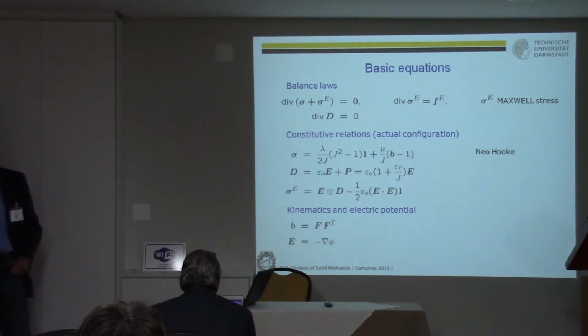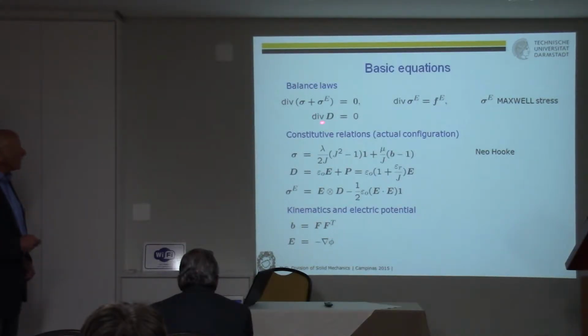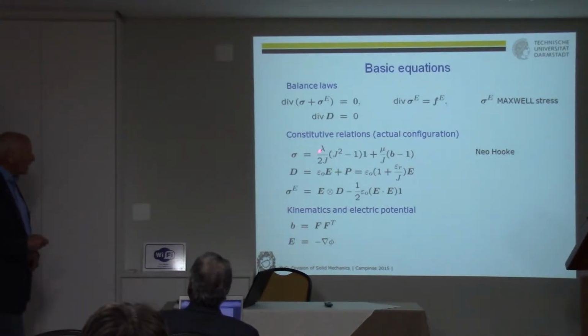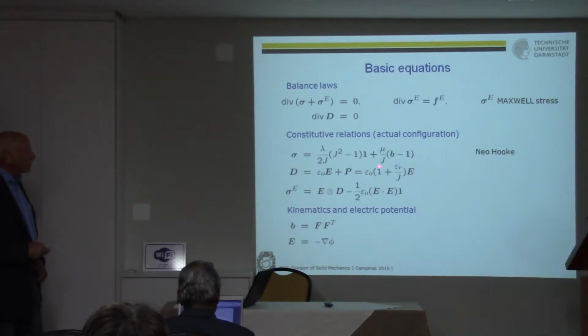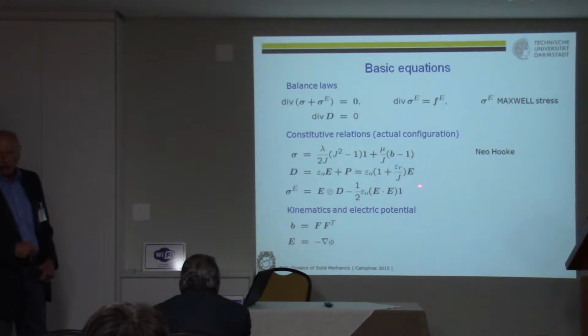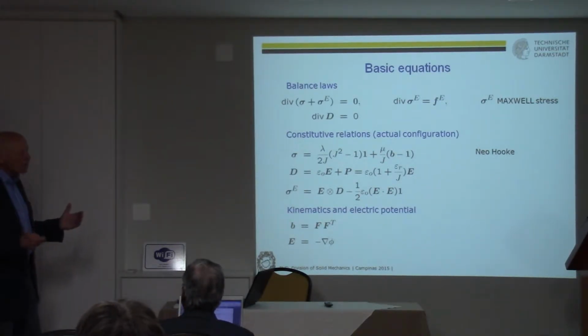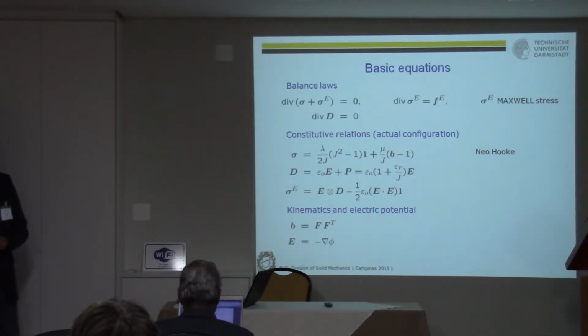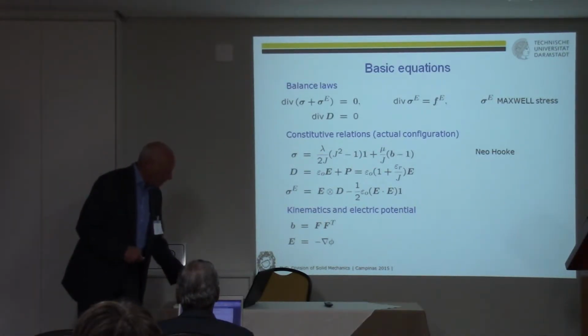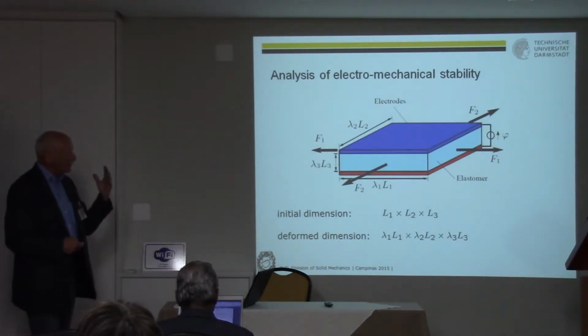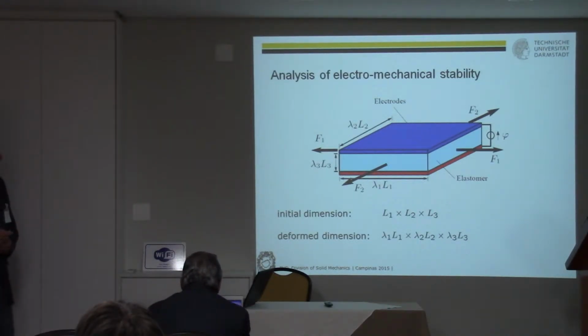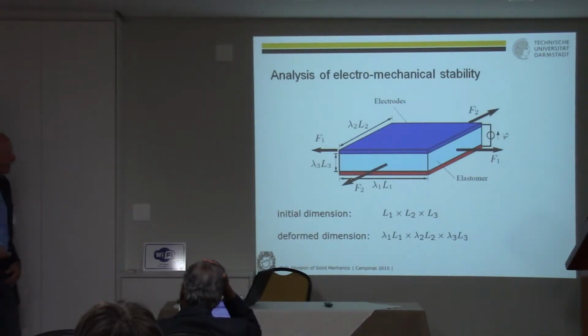Okay, again, simulation starts with modeling and basic equations. Again, the balance law here, the Maxwell stress is introduced directly, and then constitutive relation, kinematic relation, electric potential as before. And in the constitutive relations, we used for the mechanical part the Neo-Hooke law. With this Neo-Hooke law, you can simulate many different elastomers, rubber or other materials. It's not a problem, but of course you have large strains, and this means the problem automatically becomes nonlinear.